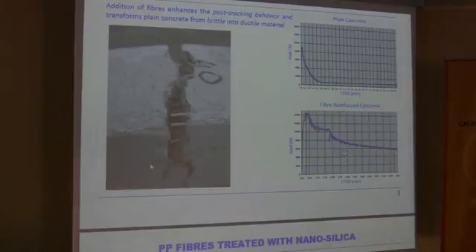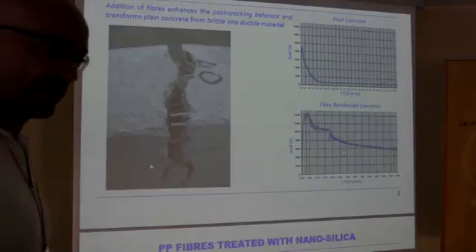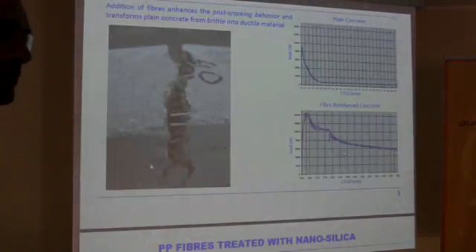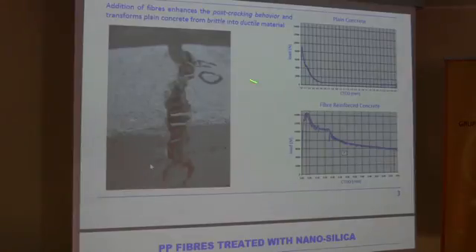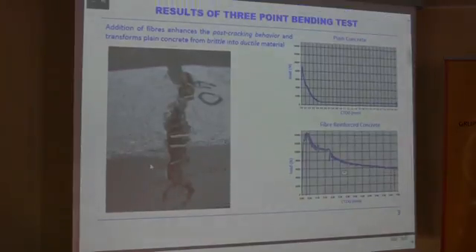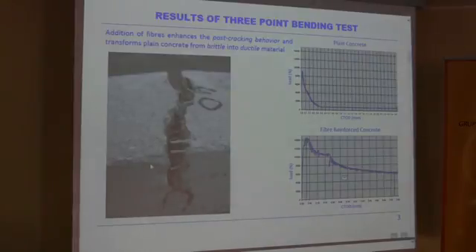The addition of fibers to the concrete mixture increases especially the post-cracking behavior of the concrete. Indeed, as soon as the crack opens, the fibers start working, thus giving ductility to the concrete and transforming the concrete from a brittle material into a ductile material. These are the results of a 3-point bending test. And therefore a larger amount of energy will be dissipated, especially due to the presence of the fibers.